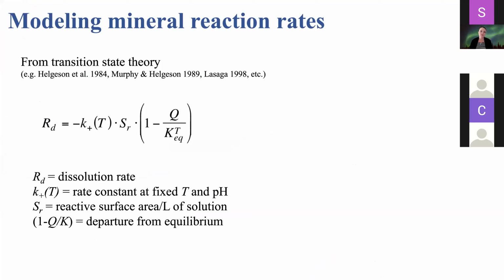Okay, so let's start talking about how we currently model mineral reaction rates. Usually we use a rate law like the one that's shown here that's based on transition state theory. Basically, the dissolution rate of the mineral is proportional to a rate constant, a thermodynamic component, and the reactive surface area. Well, we have a pretty good understanding of the thermodynamic component and the rate constant. We have a really poor understanding of this reactive surface area term.